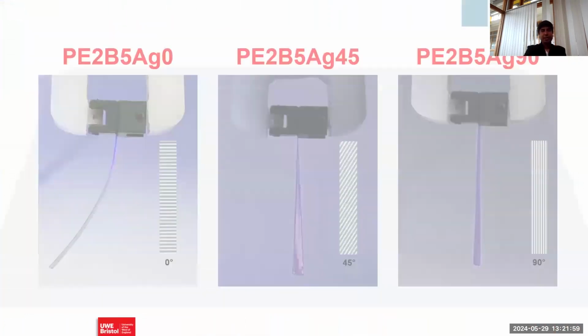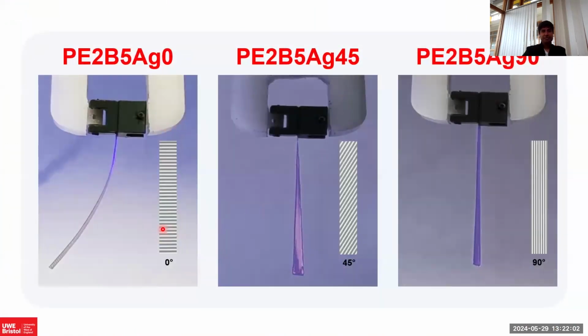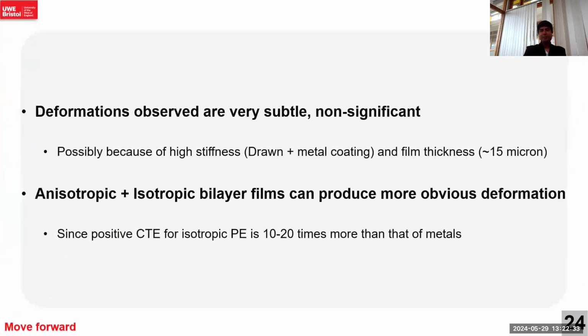But if we use different patterns like 0 degree, 45 degree, and 90 degree, and illuminate it with the UV light, we experience some deformations, like twisting and bending, within the polymeric film. But again, these are not very promising results. What we were anticipating is something similar to liquid crystals, but again, we are comparing a soft polymer with a stiff polymer, which might not be possible. So we did observe some deformations, but these are not very significant.